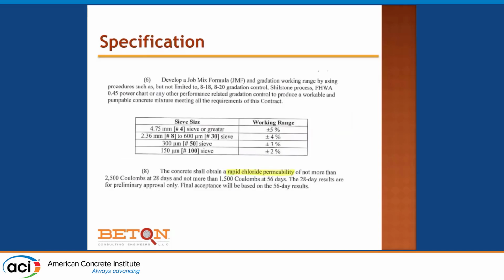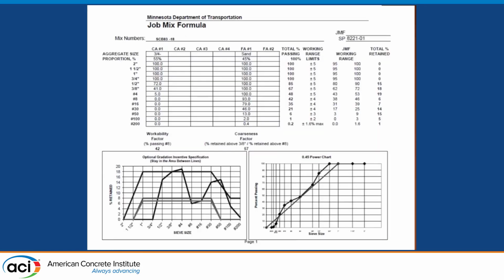And the way that it works is we develop that job mix formula just like it's asphalt, because we're using another facet of asphalt, the voids in the mineral aggregate. And that void in the mineral aggregate is the necessary paste. Until you have the voids between the aggregate particles filled with paste, it doesn't matter. And after that, you need a little bit more paste to get things to slip by one another. You can use a soft shell, hard core packing model to predict it, or you can very quickly get into the lab, do a bunch of dry rodded weights, which are now called bulk densities, and find out how much volume there is when we pack the material together based on the aggregate gradation and the relative proportions. And we then have some limits, and we control all of that.